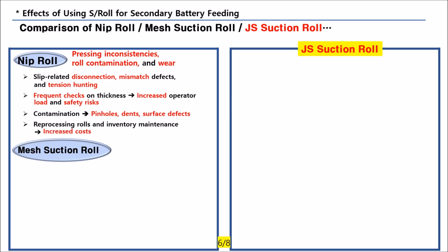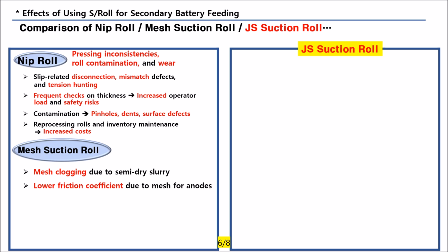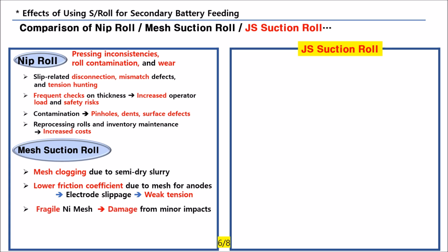costs. When using suction rolls with a mesh exterior, issues arise due to mesh clogging from semi-dried coatings or slurry, which prevents optimal performance. In the case of the anode, the mesh's lower friction coefficient can cause the electrode to slip, weakening the tension. Additionally, the nickel mesh is fragile, leading to damage from minor impacts. There are also limitations in production sizes since only specific mesh standards can be manufactured, resulting in low adaptability to varied specifications. This necessitates maintaining additional spare inventory, which further increases costs.